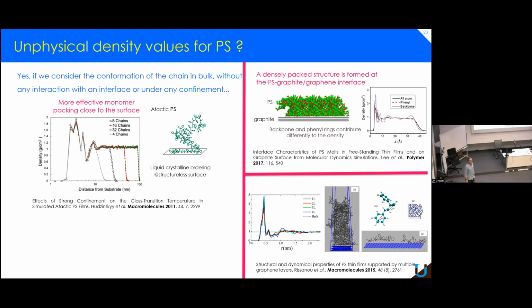Twice the film thickness. And therefore, if your argument carried over, it should be the unique function of film thickness. As soon as the film folds up, it's twice the film thickness, or three times, and so on. I don't think so. This argument is intriguing, but I don't think it's completely convincing. Those results are kind of freaky, because I completely agree with you, but the fact is that we got the result that we got. Maybe the interpretation was not correct, but with three different ways of doing it, it started to be a lot.